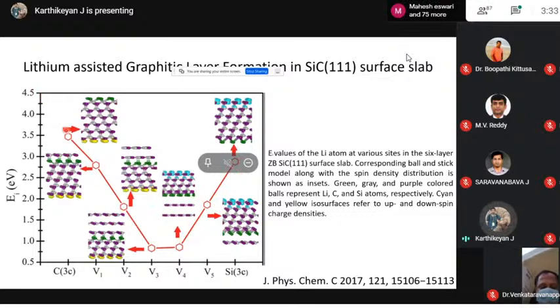These energetics are telling us that the interaction of lithium on the surface is really exothermic. It's releasing so much energy. That's what in the experiment also they have found. When they add the lithium first, it gives a very high potential. Then when they add more and more lithium, the potential comes down and it becomes a very slight potential when the lithiation is happening in the bulk.